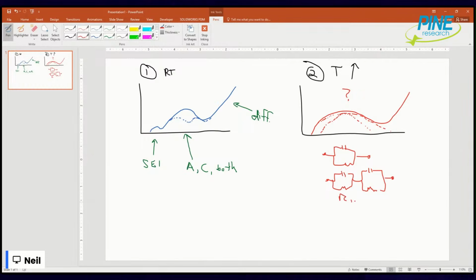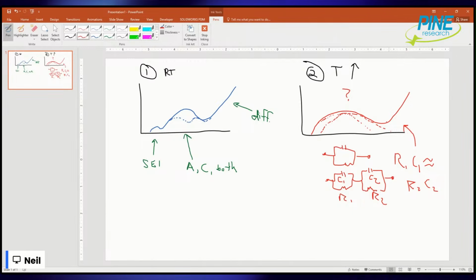So this is R1, this is R2, this is C1, and this is C2. In the case that R1C1 is roughly equal to R2C2, you get this situation. That's because the 2 processes have similar time constants, for whatever reason. Now, when you increase temperature, kinetics changes, not always the same for everything. So your anode, your cathode, your SEI, the speed at which these are taking place may be very similar. And so that's why these are coinciding, right? That's one explanation for this.